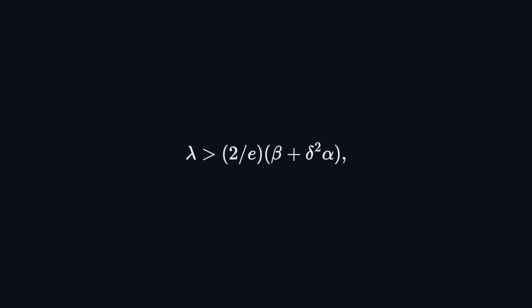And the line between settling and runaway is one inequality. Lambda greater than 2 over E times beta plus delta squared alpha. Lambda is heating. Beta and delta squared alpha are the cooling coefficients. Heating must exceed cooling by a factor of 2 over E, about 74%. That is the flash criterion, the entire phenomenon in 7 symbols.